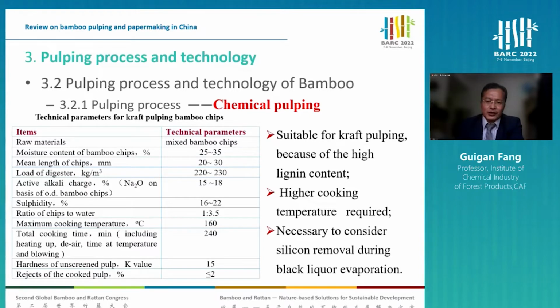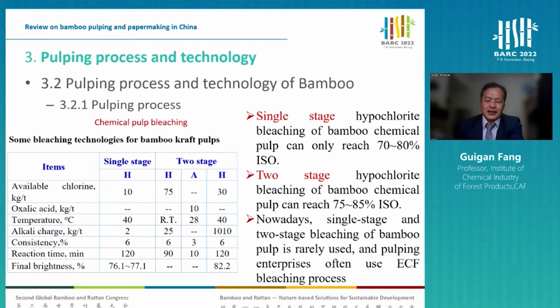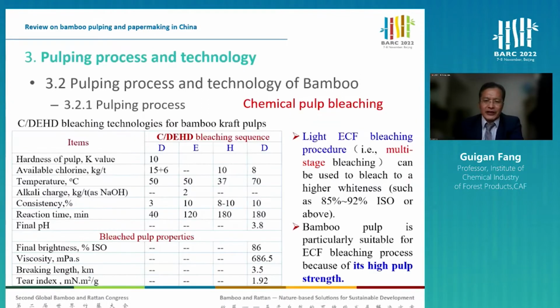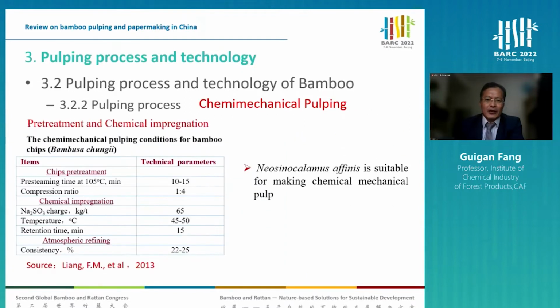And actually, the process and technology is mainly the sulfate method, but we need to consider the silicon removal in the process. Previously, we usually applied single stage and two stage bleaching, and the rate can reach 75 to 85%. Currently, we often use ECF. The ECF can realize higher brightness and better quality. Actually, it is an ideal solution for quality bamboo paper production. And also the chemi-mechanical pulping is applicable.